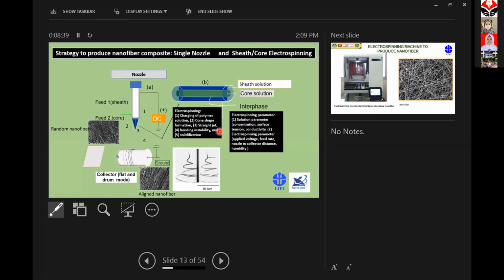So by using the electrospinning process, we can make two types of nanofiber. We can make random nanofiber, for example here, and we can also make aligned nanofiber if we use a high-speed drum collector. This is the parameter to make nanofiber by using the electrospinning process.